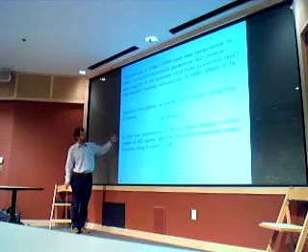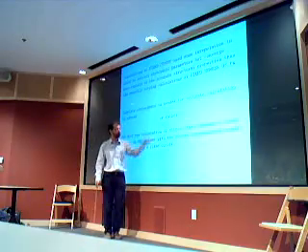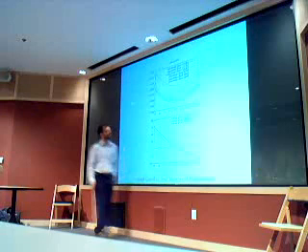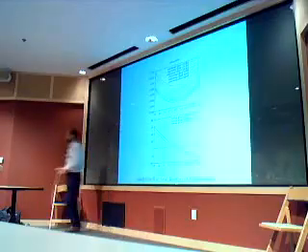So rather, you need good convergence so that the stress, which assumes a fixed number of plane waves, agrees with a smooth interpolation of the energies. And this happens because when the cutoff is large, the smooth curve that you obtain at a fixed number of plane waves becomes closer and closer to the calculation that you obtain at fixed cutoff.